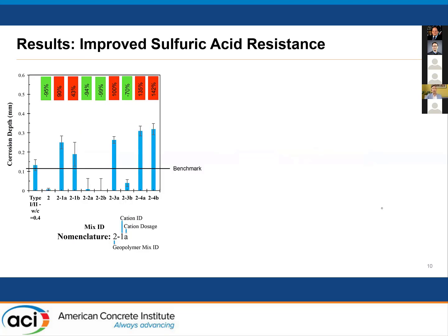How did they work experimentally? So here is a graph showing the 7-day corrosion depth of the mixtures we tested in sulfuric acid. We are comparing the performance of all of the geopolymer mixes that we tested to the OPC type 1-2 control as our benchmark, because that was the best performing.